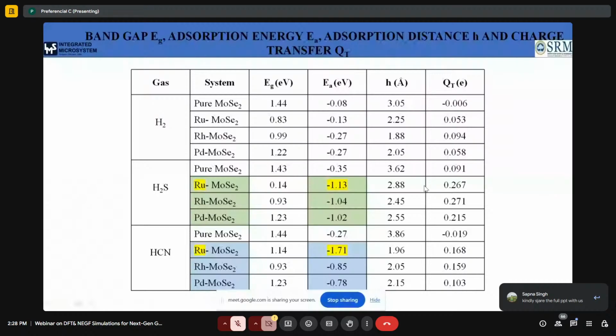When we come to the HCN system, again compared to pristine, all other systems are showing a better adsorption energy value, but comparatively, the ruthenium doped MoSe₂ is showing better adsorption with the lowest value, minus 1.71, and a very good charge transfer compared to all the HCN systems, 0.168 electron. So from this adsorption energy analysis, what we observed is that the doped systems as well as the pristine MoSe₂ systems do not act as a good sensor towards hydrogen. Instead, they can act as a good sensor towards H2S gas as well as HCN gases.